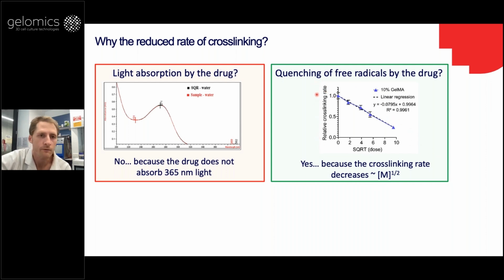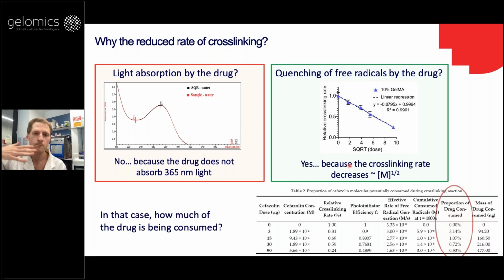So plotting the relative cross-linking rate against the square root of the drug dose, we see that it does agree with that square root dependence. So that supports the idea that the drug is actually quenching some of the radicals and therefore slowing down the reaction rate, and that's why that drug-loaded material was softer than the non-drug-loaded material. But we can go a bit further.